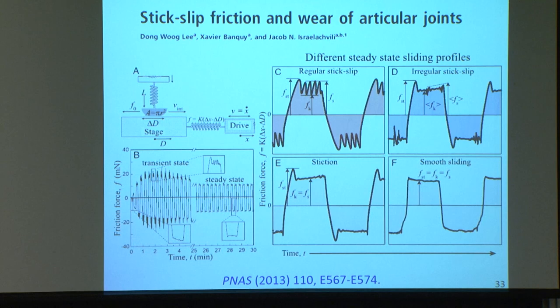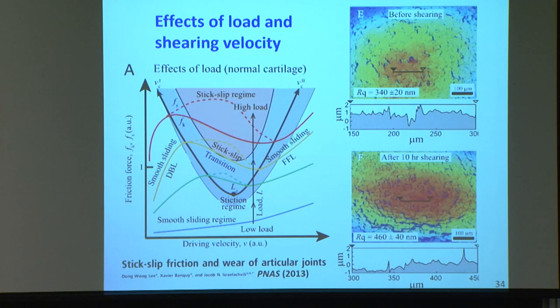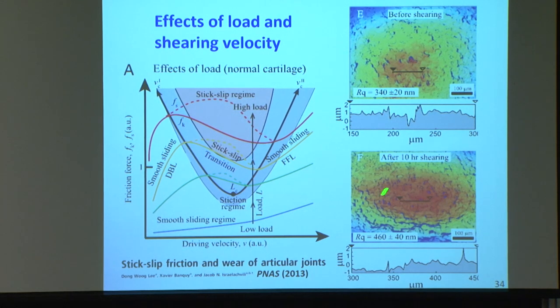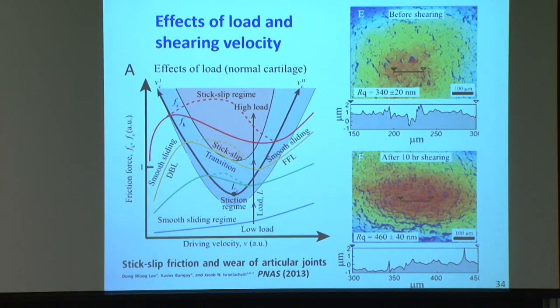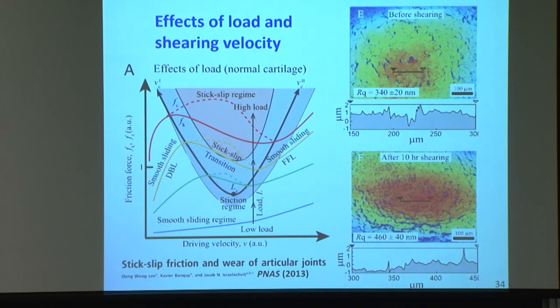But the main thing I wanted to say is that we did these experiments and found that the damage that was done occurred in the regime where there was stick slip. So it didn't depend so much on the load or the friction coefficient. So long as the friction is uniform, the sliding is uniform, doesn't matter if the friction coefficient, which is defined as the friction force divided by the load, can be high, but that doesn't cause damage. Well, it could, but not in many cases.